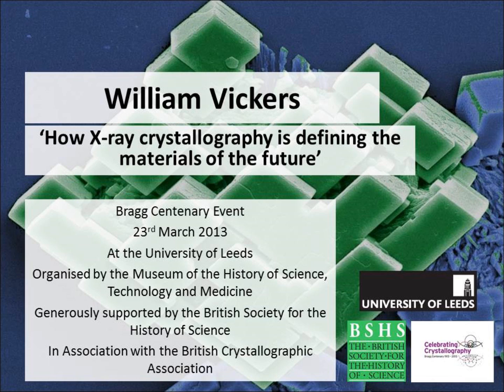But as we heat it and put energy into it, the atoms are able to move around, and they start to form crystal structures, and we can see these very well-defined peaks. As we increase the temperature, we see different peaks forming, and these are different crystal phases. By using X-ray diffraction, we can see what these crystals are and their shape. By looking at the shape of the peaks, we can see if the crystals are stressed, or if the composition changes throughout them, and then apply all this knowledge to form a material that has all the properties that we want.